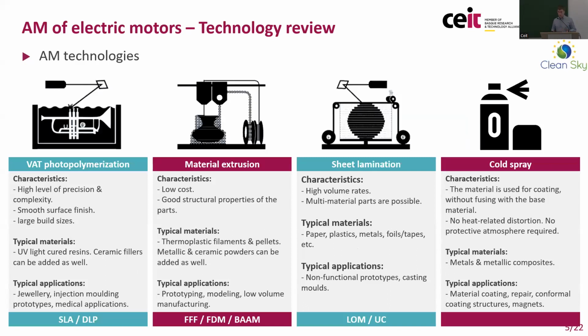A different, particular case that is quite different is the cold spray technique. Instead of trying to bind those powders by applying pressure, or sorry, by applying energy into them, what it does is just spray the material at high speed onto a surface, therefore obtaining a layer of material. So it's more of a coating process rather than a manufacturing process itself, but it's quite interesting, and it has been successfully applied to the manufacturing of permanent magnet materials.